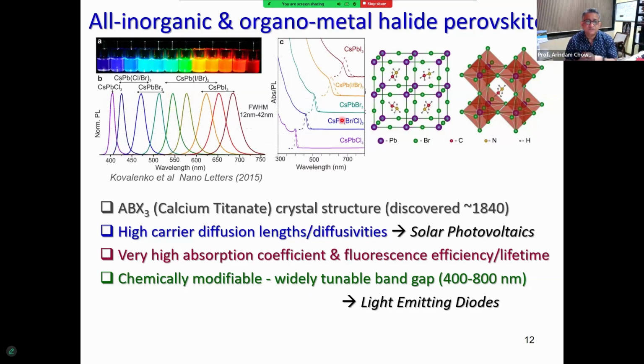And this was actually shown very beautifully by Kovalenko back in 2015. He generated this wide color gamut of nanocrystals with very narrow, very sharp spectra, and he could control the emission from 400 nanometers all the way to 700 nanometers in the entire visible region. You can see how sharp the absorption peaks are as well.